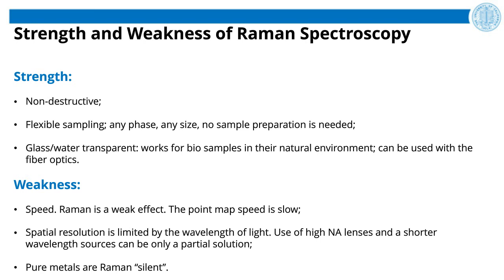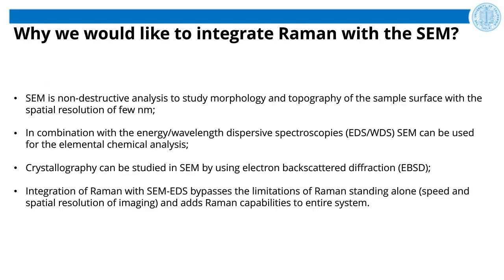Well, why would we like to integrate Raman with the SEM? Partially it's clear from the previous slide. SEM is also a non-destructive technique to analyze and study morphology and topography of a sample surface with high spatial resolution, down to a few nanometers. Then SEM-EDS, the coupling of the SEM with energy dispersive and wavelength dispersive spectroscopy, is very common these days, and those provide elemental composition of your materials. So basically, SEM and EDS can provide elemental chemical analysis of materials. Also, with SEM, we know that we can study crystallography by coupling SEM with electron backscattered diffraction attachments.